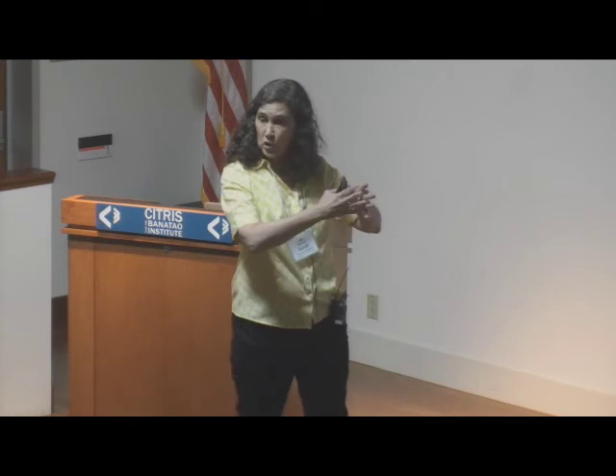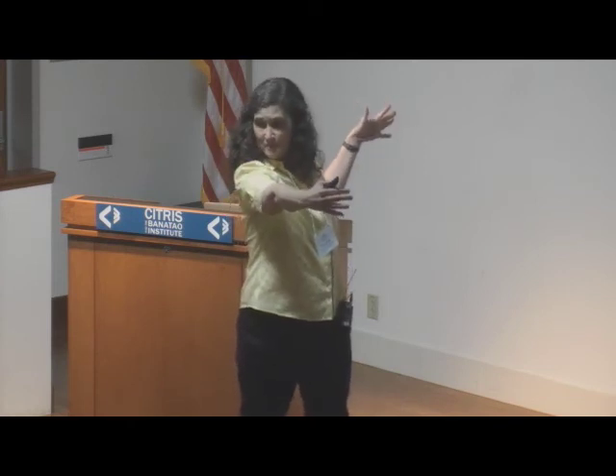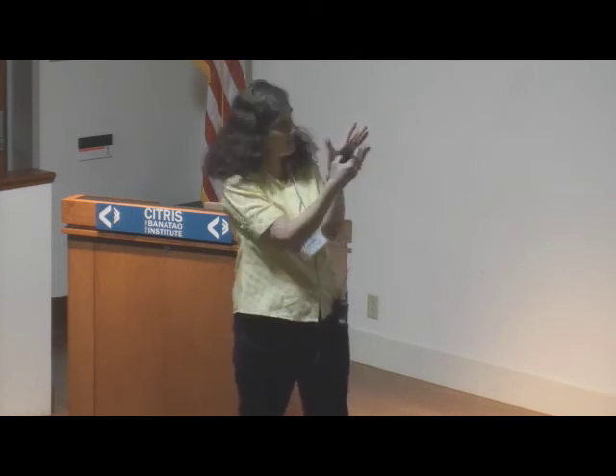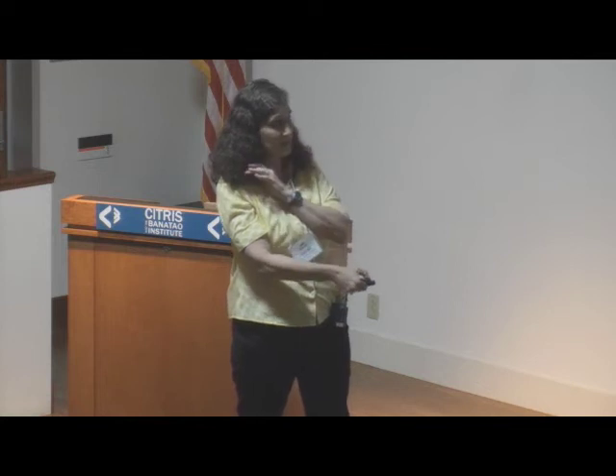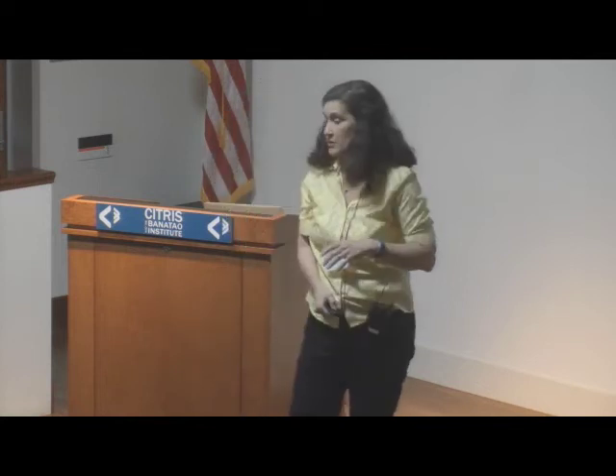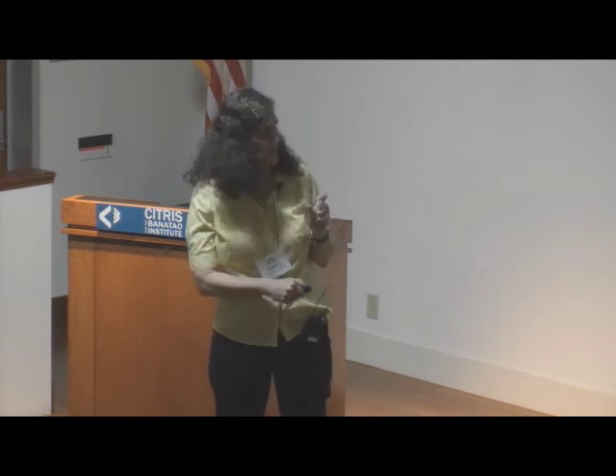If this were a long event, we would expect a really broad diffusion profile. A short event, we get a very small diffusion profile. We have a very small diffusion profile here. It's half a centimeter or so. So that square root Dt is a smallish number. We don't have a lot of constraints on the diffusivity of lithium, but we have some. And so we can estimate the duration of this fluid flow based on this profile.